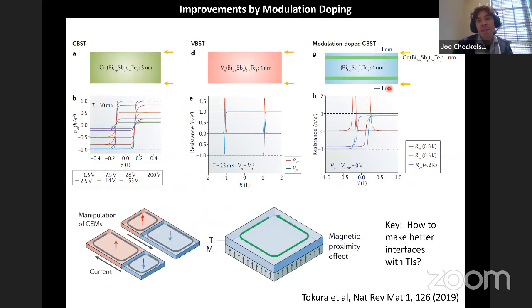This technique, which I mentioned here, I think a little bit splits the difference there, where instead of doping everywhere, you kind of dope in some specific places. So I think this is good, but because it's still grown at a finite temperature, these interfaces are not atomically sharp. So you still get some bleeding of the chromium ions away from where you really want them. So using van der Waals materials, you would then overcome that disadvantage because those are atomically sharp in the sense that just at room temperature, you put them together and there's no intermingling across the interface. The negative point to those systems, though, can be that it can be hard to get a lot of good magnetic exchange across that interface, meaning how much do the electrons in one layer really feel the magnetism in the other layer.